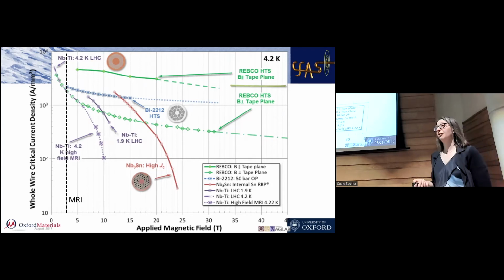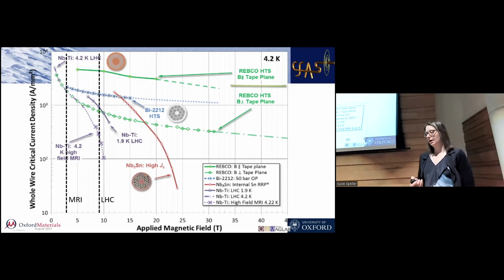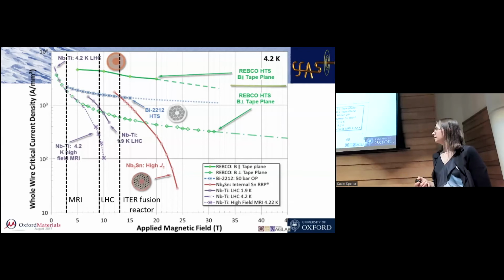If we go to the Large Hadron Collider, which is a superconducting machine as well, that needs 9 Tesla. And we do still use niobium titanium because it's by far the easiest superconductor to use, but we have to cool it now. We can't use it at 4 Kelvin, we've got to use it below 2 Kelvin to get that to work. Okay, we can push its performance out to the right by cooling it a bit more. ITER, the big tokamak that's being built, needs about 13 Tesla or so. So we can't use niobium titanium, these purple ones. We've got to use the next material, which is niobium-3 tin.